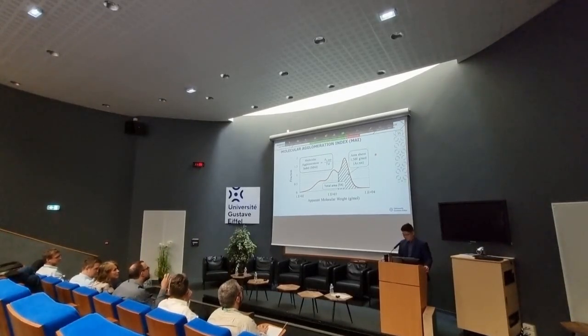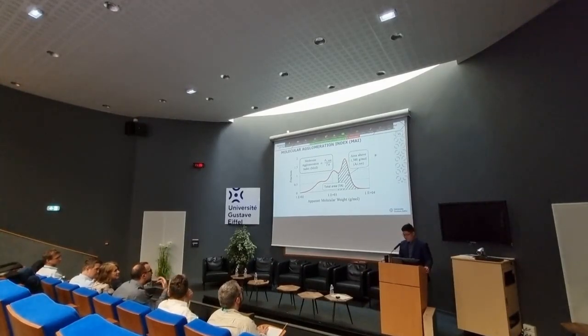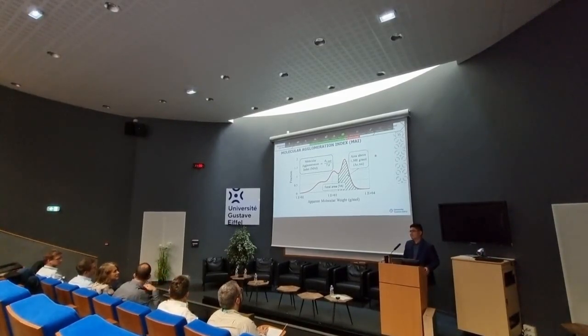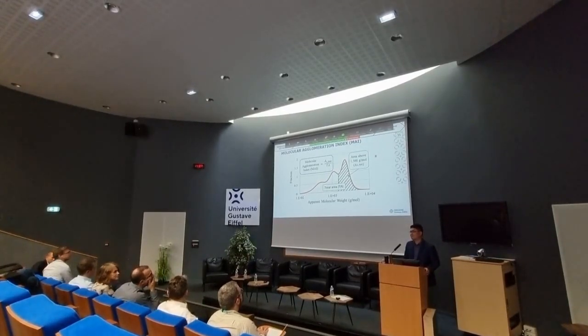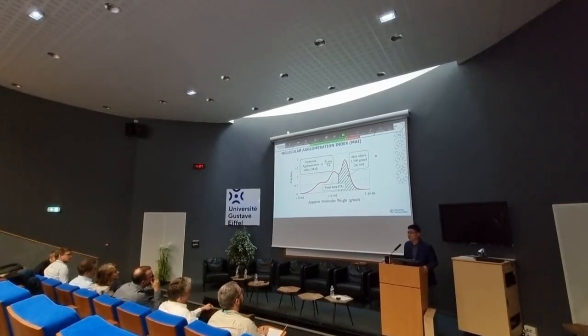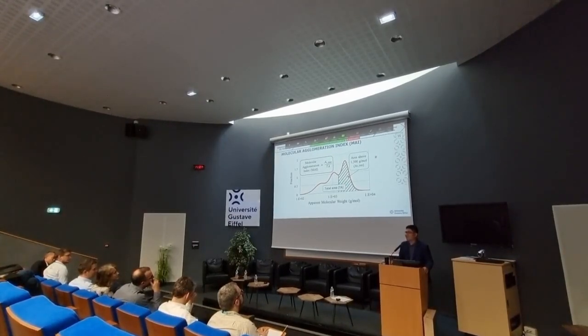Yes, gelation. Because if you have more or less solid particles such as asphaltenes, and you reach a certain volume fraction around 0.6, you can have a percolation of these solid particles, and that could explain the change of mechanical behavior and failure. So what do you think of that? Yes, well, this was actually one of the hypotheses that we were working on. This possible solid-gel transition that could probably happen at around 0.58. So, yeah, I'm very glad that it seems to be in line with what is observed in polymer science.